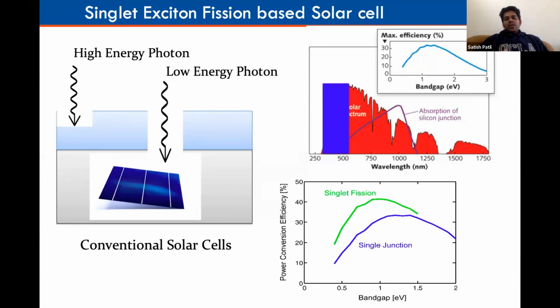It does not really take away the other part of the spectrum. If you take away this blue part of the spectrum, with high energy, wide band gap organic molecules coating on silicon, it can boost the efficiency from a thermodynamic limit for silicon, which is close to 30%, 1.1 eV here. The calculation suggests it can go up to at least 43%. So you can go beyond the Shockley-Queisser limit, but you're not really complicating the device design. It's a very simple, thin layer coating of an organic dye on the surface of silicon, and you're boosting the efficiency beyond the thermodynamic limit. So that's the idea of using molecules in this work.